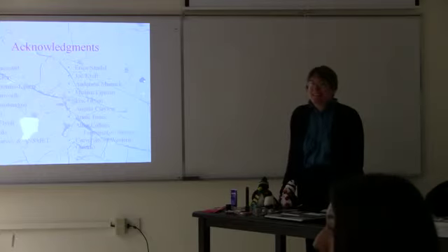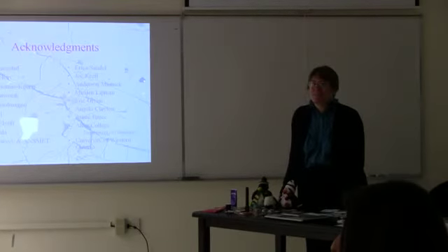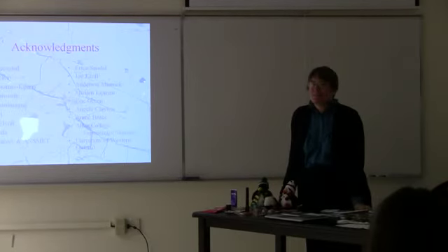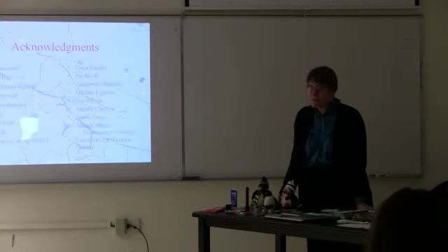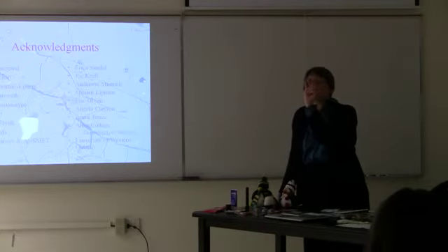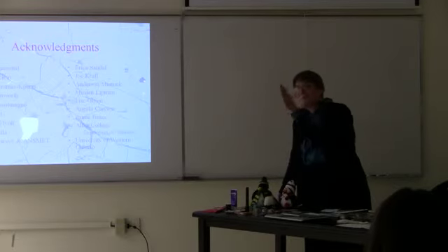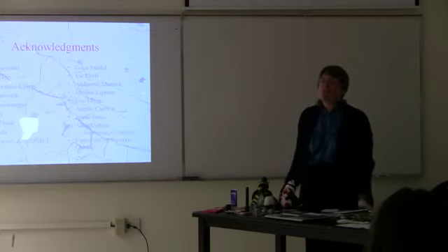The FTIR spectrum that you showed, I may have missed this. Which rock was that of? That was of a piece of ordinary chondrite that we had put in an oven at 150 degrees for 3 months. Wow. And that was within about a millimeter of the surface. So we had penetrated at least a millimeter, hydrating it. There didn't appear to be much further in.